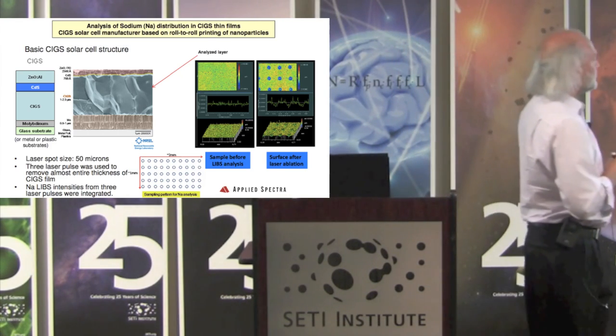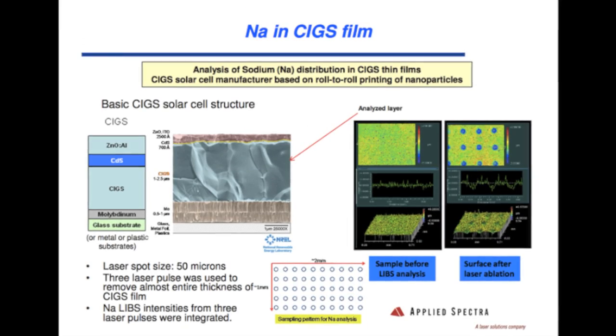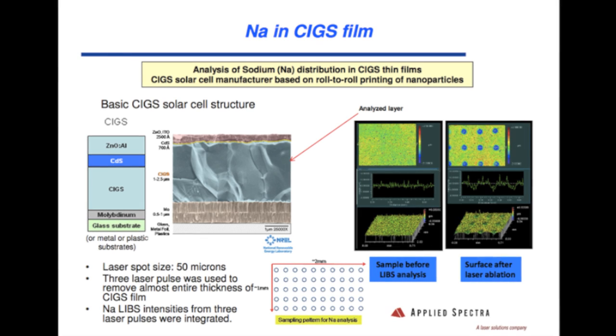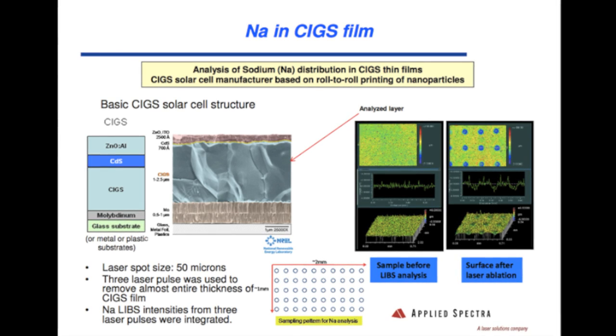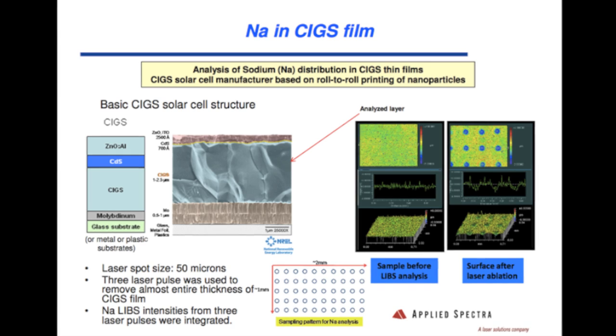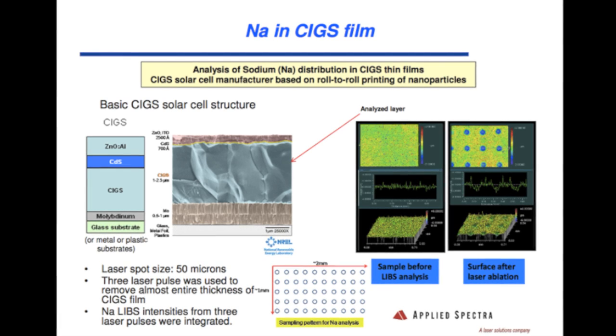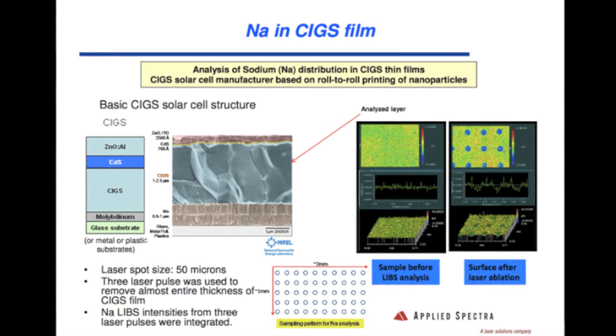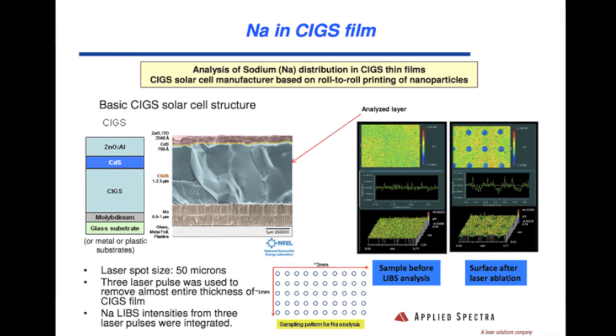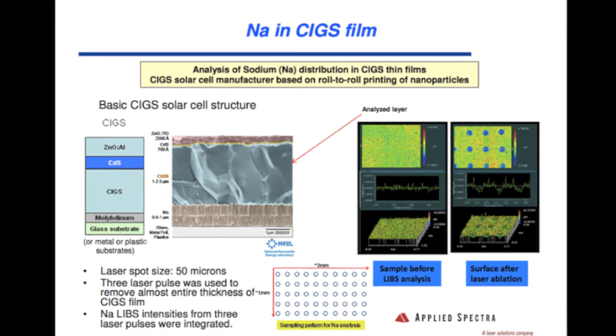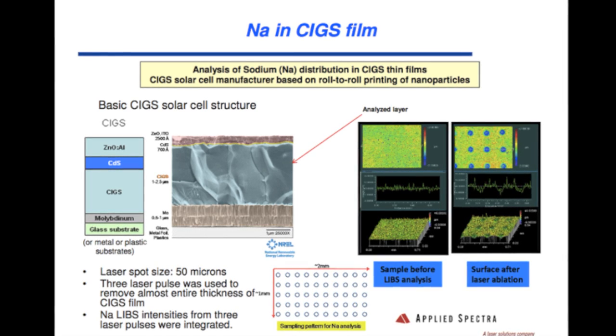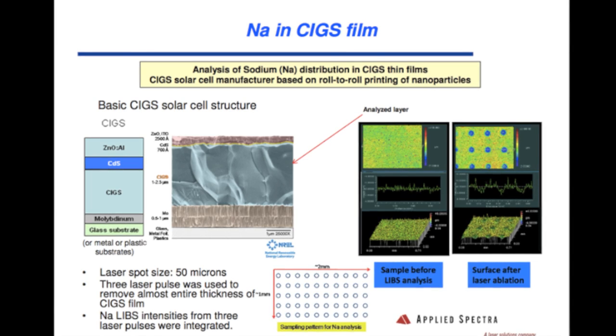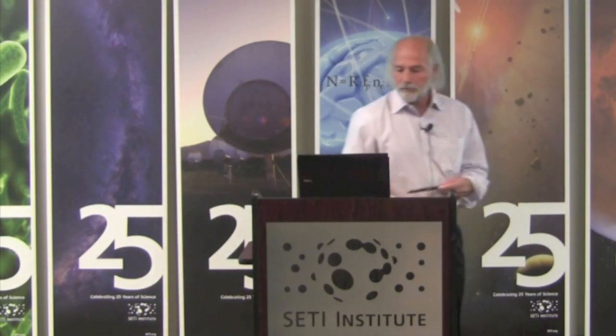And this is again another CIGS film where we're looking at sodium impurities across the surface. So this is just the laser spot hitting different regions across the top of this CIGS film. And we dug into the CAD sulfide, the CIGS layer itself, and they wanted to see what the sodium impurity was. So you can look at impurity distributions in materials, and I'll talk about the different spot sizes. What is the spatial scale?